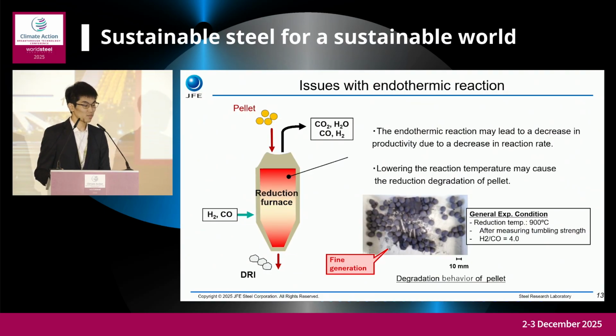This slide describes the various problems of endothermic reactions. As I have said many times before, reduction by hydrogen involves a large endothermic effect and the reaction rate will decrease, and there is a concern that the lowering of the reaction rate will cause a decrease in productivity of the shaft furnace. Also, as I mentioned before, there is a concern that the decrease in temperature with endothermic reaction may promote the reduction degradation of iron ore pellets.